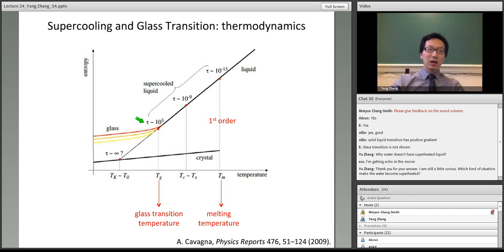So in this paper, the authors say that the glass transition is defined at a relaxation time of approximately 1,000 seconds. But usually we try to define it as the relaxation time reaching 100 seconds, or in terms of viscosity, 10 to the 13 poise.